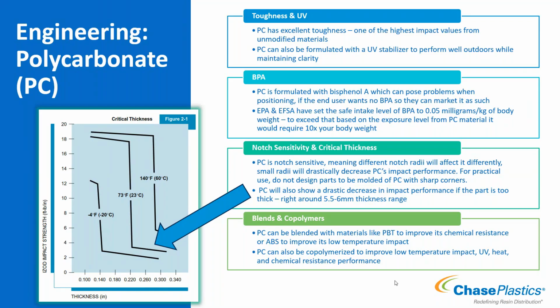Polycarbonate also has what's called a critical thickness, where if you get it too thick, or design a part too thick, you also lose impact value. For polycarbonate, that value is right around 5.5 to 6-ish millimeters thick, and once you get to that, you lose all of your impact value. If you follow the arrow pointing over, you can see impact performance depending on the temperature range. But if you're at room temperature, at 73°F, you're up around 18 impact, foot-pounds per inch impact, so excellent impact. You hit that critical thickness and you drop all the way down to about a 3 impact.